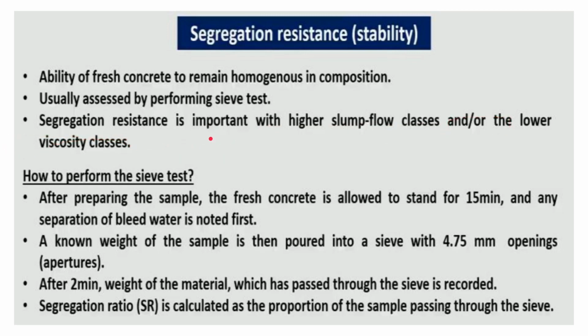It is the ability of fresh concrete to remain homogeneous in composition, usually assessed by performing the sieve test. Segregation resistance is important for higher slump flow classes, as we just studied, where the VMA comes into the picture, and for the lower viscosity classes. So that's why the VMA is important. So how to perform the sieve test? Here we basically perform the sieve test.